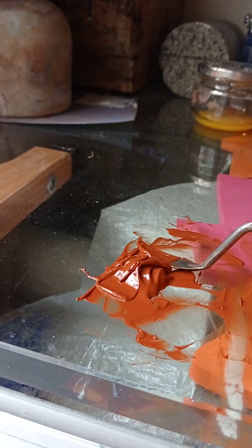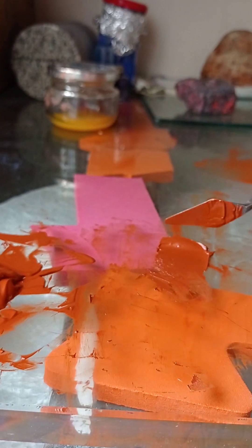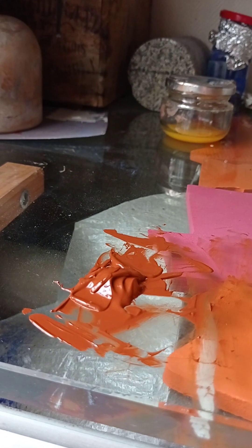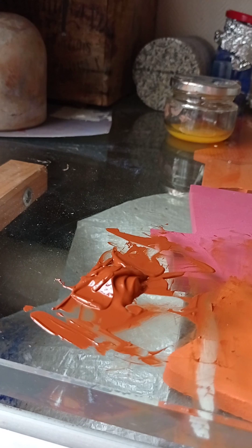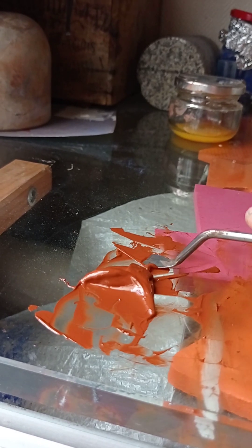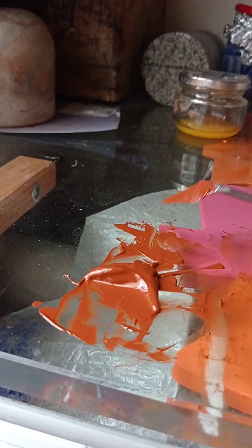If you want to modify this long paint in order to obtain a modern short consistency, you can add some special rheology modifiers like hydrogenated castor oil or aluminum stearate. But in ancient times, the old masters had a very simple product which could be used for the same purpose, and which is very simple to find: it's egg yolk.